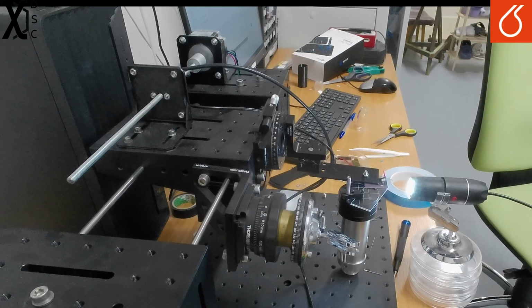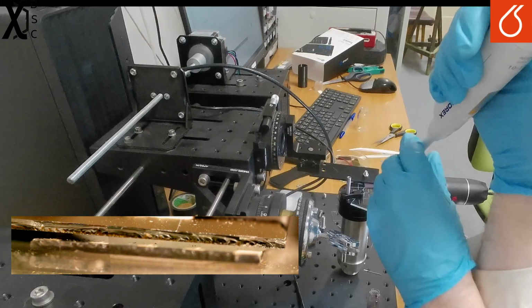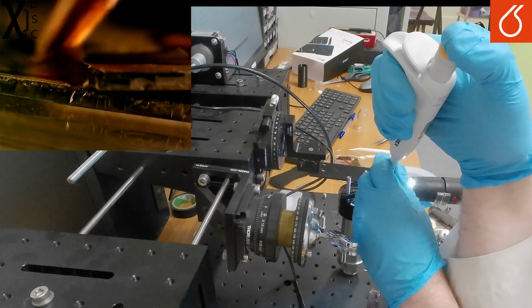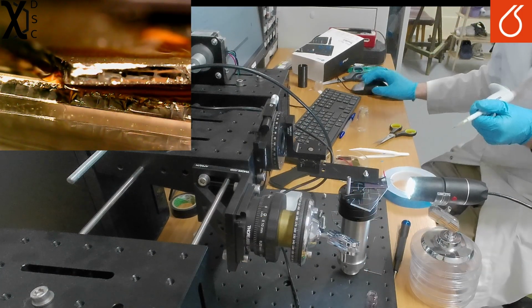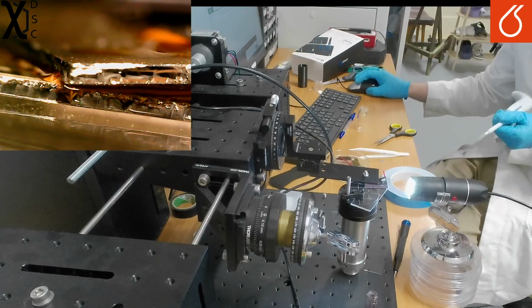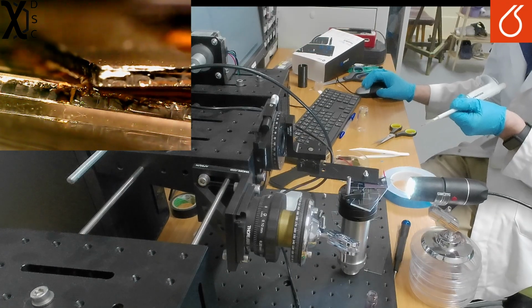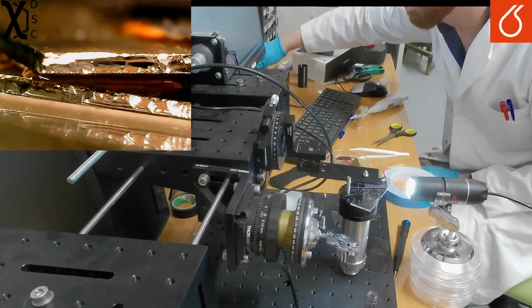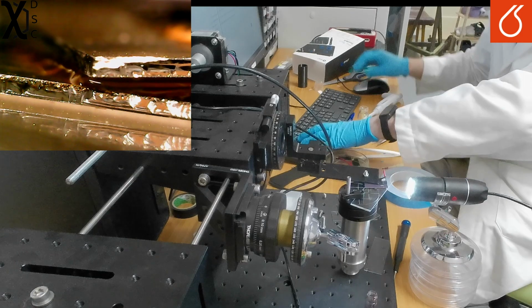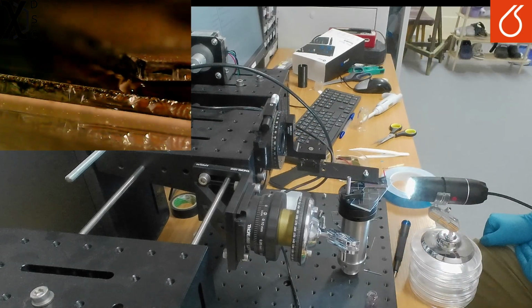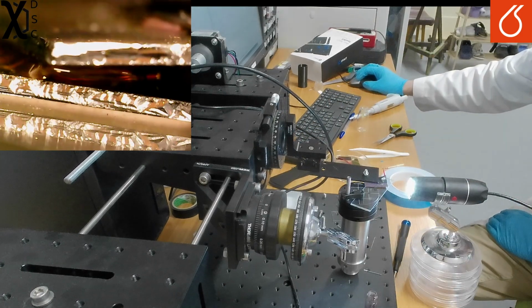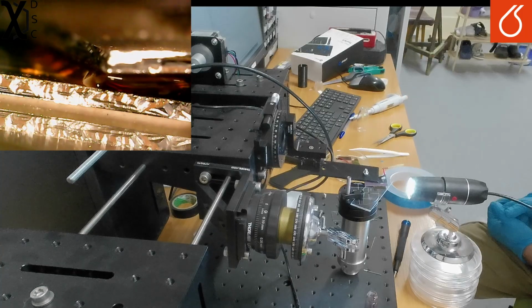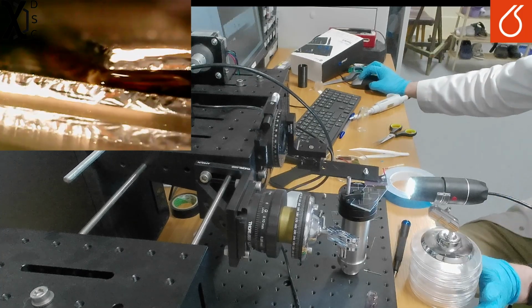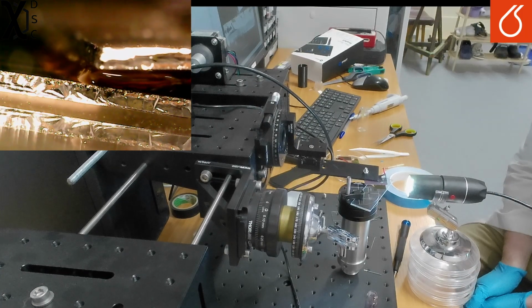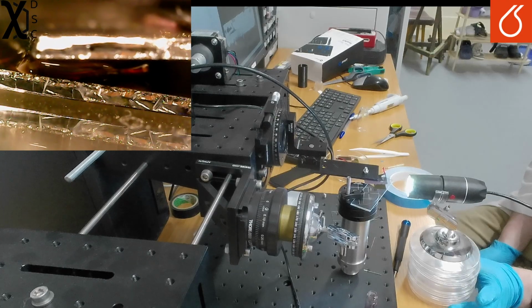The final method I will be showing is blade deposition. This involves scraping a blade along a surface coated with a solution of the desired material. There appears to be two ways of doing this method. Either the compound is directly applied to the surface and then the drops are spread by the blade, or the compound is applied to the blade and the surface tension is used to drag the solution along. The most common method by far appears to be applying drops to the surface and dragging it along. However, here I do it via applying the drops to the blade.